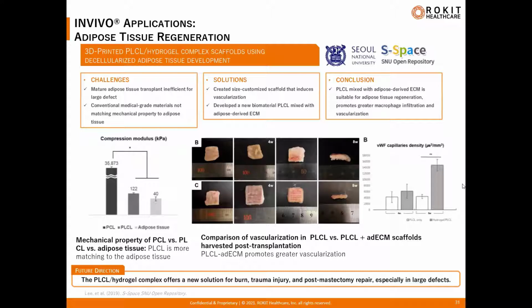This is an example of the application in adipose tissue engineering using bioprinting. Conventional medical grade materials such as PCL are often used in breast reconstruction and nose reconstruction. But the problem is they do not match the mechanical property of the adipose tissue. So this group first developed a novel biomaterial called PLCL, and they mixed it with adipose-derived ECM. Using bioprinting technology, the group created a size-customized scaffold, which when implanted into mice, promoted adipose tissue regeneration with adequate macrophage infiltration and vascularization. The group confirms that bioprinting combined with this new material and ECM can offer a new solution for burn, trauma injury, or post-mastectomy repair, and especially with applications in large defects.